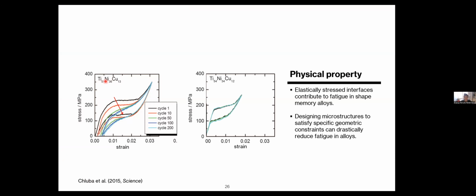So they changed the titanium, nickel, and copper in careful parts. This new alloy satisfied the special lattice parameters necessary to eliminate the elastic stresses at that interface. And now they could cycle this material for over 200 times, and the fatigue that this material experienced before is pretty much eliminated, or highly reduced, in this example. And so this kind of inspires my work, in which you have these special combinations of lattice parameters that can be used to eliminate fatigue in material.